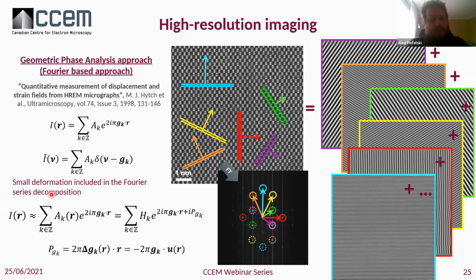So what is interesting in this GPA approach is that it includes the small deformation in the Fourier series decomposition. So it's technically not correct to do that because we are breaking the periodicity here. But if the deformation is small, we can accept that this coefficient that is supposed to be constant varies with space. And this coefficient has a real and an imaginary component. And this imaginary component would be this extra phase that's going to be related to delta G. Delta G is going to be our variation of the G lattice here.